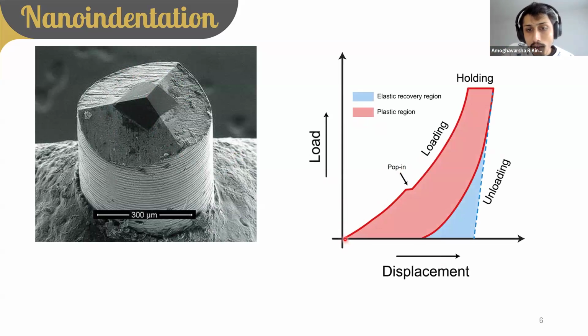So here we can see whenever we indent the sample, the load goes on increasing and also the displacement goes on increasing. And once we reach a specified load, which we can change anytime, we give a little bit of holding time. Holding time is because whenever we indent a sample and remove it immediately, the sample will lag behind the tip, and we cannot get the accurate measurement of the mechanical properties of the crystals. That's why a little bit of holding time is given and then unloaded.